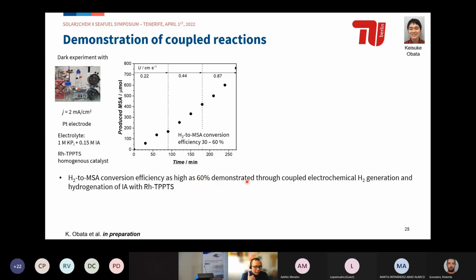I don't have time to show the proof here, but we show in our study that this reaction happens through the coupled concept. We first form the hydrogen, and then the hydrogen that is produced in situ is used to hydrogenate the itaconic acid. So we did not hydrogenate itaconic acid directly on the surface of the electrode.